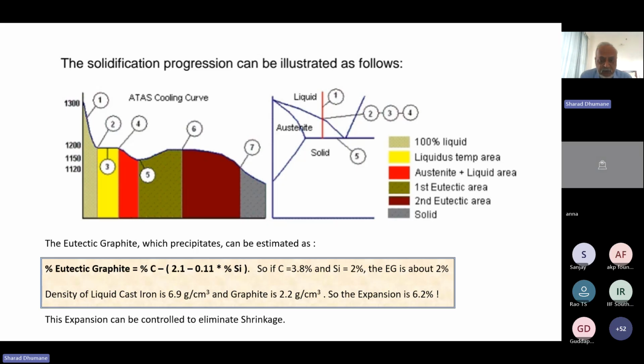Okay. But here I think the most important point is that when graphite precipitates, the volume of liquid increases, and if our inoculation, our melt quality, and our processes are correct, then all this expansion is available. The benefit of this expansion is available, and then we can nicely, in a very structured manner, control our solidification shrinkage. That is the point which I want to make here. But this expansion will not be available if our melt quality is not right. So this is the link, the impact of melt quality on shrinkage defects in ductile iron. This is the basis of the whole discussion today. Okay.